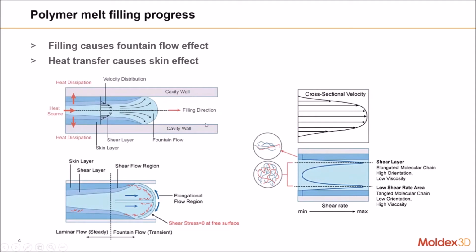In this slide, what I want to highlight is that we only see 2 things here. We divide this melt front into 2 sections, front and back. In the front section, at the front of the melt front, ideally, shear stress should equal 0 because that is a free surface, no friction, and the polymer is randomly oriented and no shear stress should happen here. It's like a free surface. So this is the first point I would like to share with you in this slide.